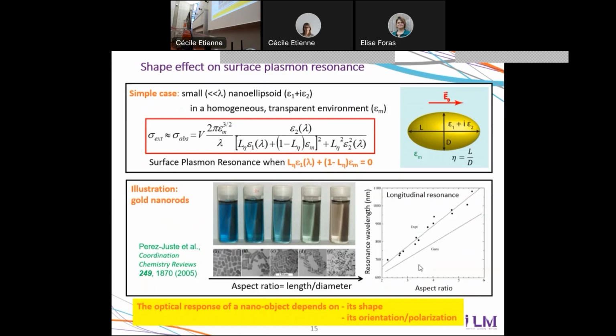So this shows that the plasmonic resonances of metal nanoparticles are quite tunable by playing with the shape of the particles, and it's very useful, for instance, for biological applications, which would require infrared resonances. These resonances cannot be easily achieved with the spheres, but they can be easily achieved with elongated objects, such as these ones.